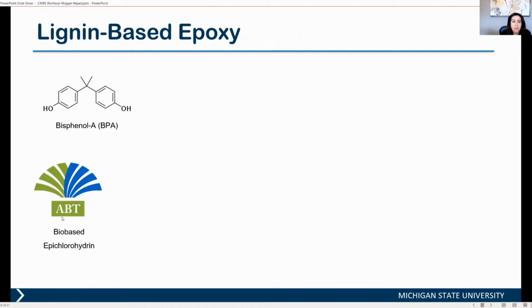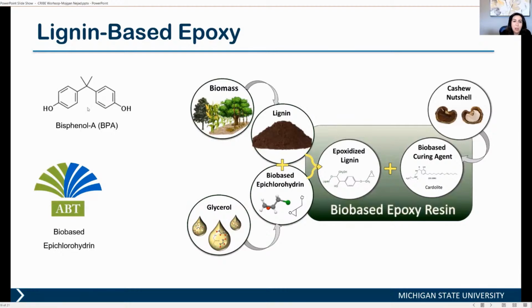And this company, Advanced Biochemical Thailand, is producing bio-based epichlorohydrin. For epoxy, these are the two main compounds, bisphenol A plus epichlorohydrin. In one project, we replaced 100% of the bisphenol A with unmodified lignin. And using 16 different lignins, we tested the reactivity with this bio-based epichlorohydrin that we got.